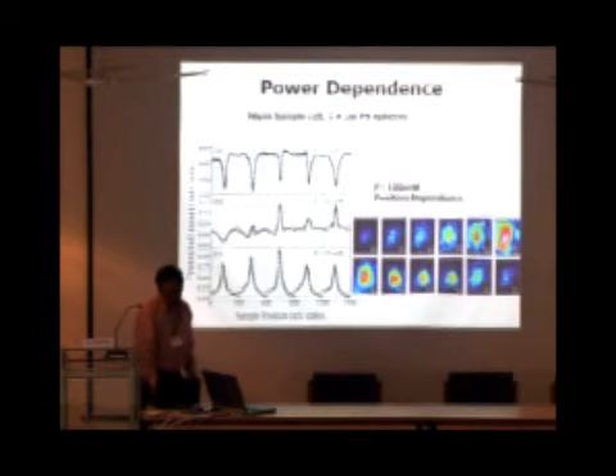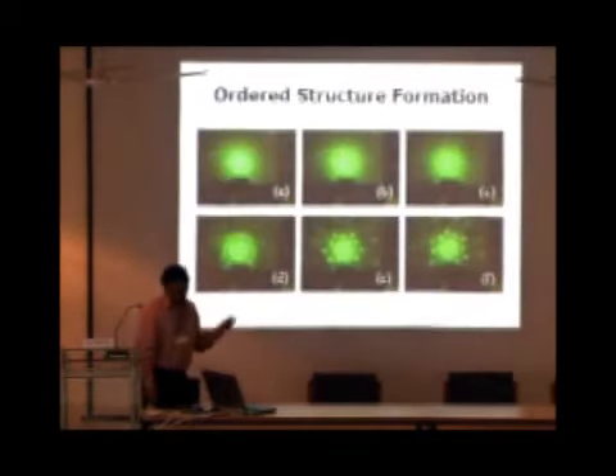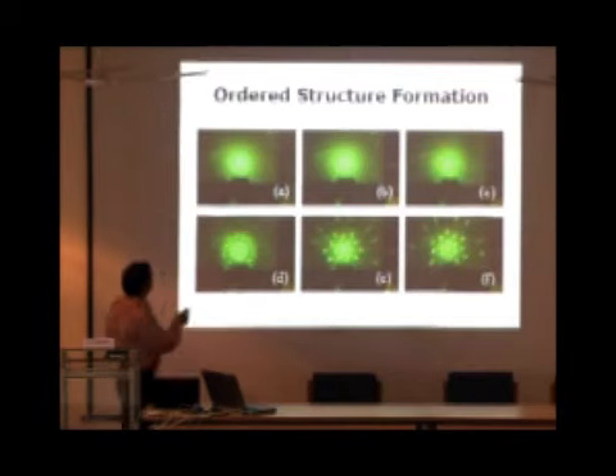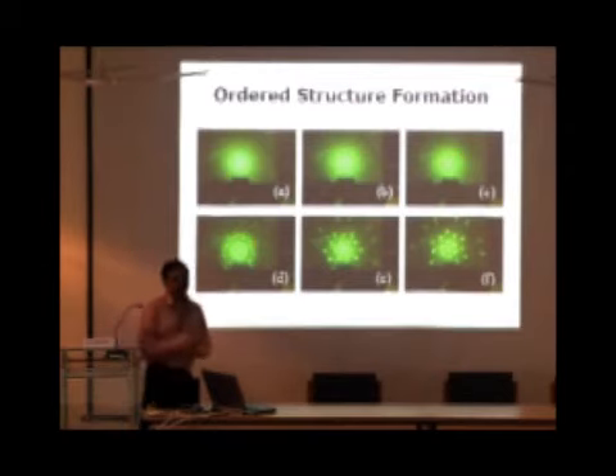The best way to look at it is the diffraction pattern. Initially it's a completely random system - you see the Debye-Scherrer ring which evolves into a clean diffraction pattern, showing that you do have a periodic structure.